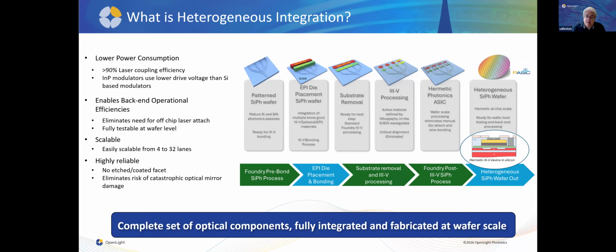Once those processes have been completed, the whole thing is encapsulated in a thick layer of silicon oxide, so it's passivated against the elements. And what you get out at the end is a wafer that can be tested and handled as any other type of silicon photonic wafer can be. That means we can integrate into a standard OSAT backend, which operates at scale with high volume and pretty low cost as well. So there's no real special handling because you have indium phosphide devices inside.